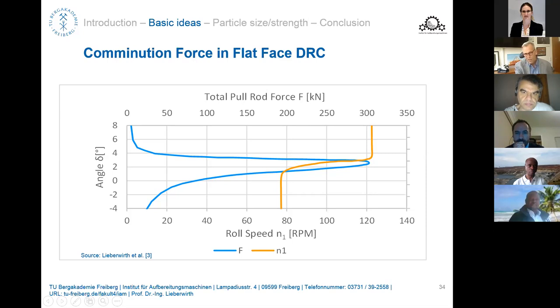So if you don't give the material enough space to escape or to flow onto sides, and you remember single particle comminution, we are usually talking about a filling ratio of 15% solids in the crushing gap. But even if the average 15% is achieved, if you don't allow every single particle this 15% solid ratio only, then you might create substantially high forces. And not only the high forces, coming along with these forces is also the production of a lot of fines. And in many cases, you are not interested in the fines. In this case of the real crusher I've shown before, the people wanted to have this fine material. That's why they closed the gap too much, perhaps. But in many cases, you don't want to have the fine material, and so you should avoid also these high force peaks.